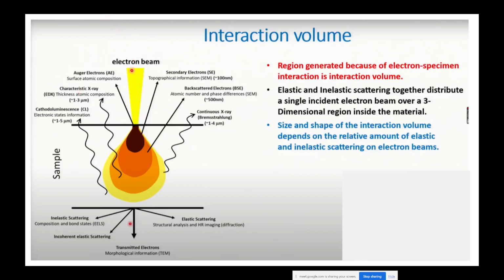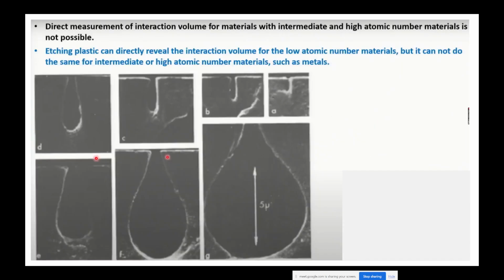Just now you can see your electron beam is coming, and here is your sample. What will you get? Secondary electrons, backscattered electrons, continuous X-ray, Auger electrons, characteristic X-ray, and cathodoluminescence. This is the depth of your sample, so you will get the interaction volume. The size and shape of your interaction volume varies, depending on the scattering, elastic and inelastic.